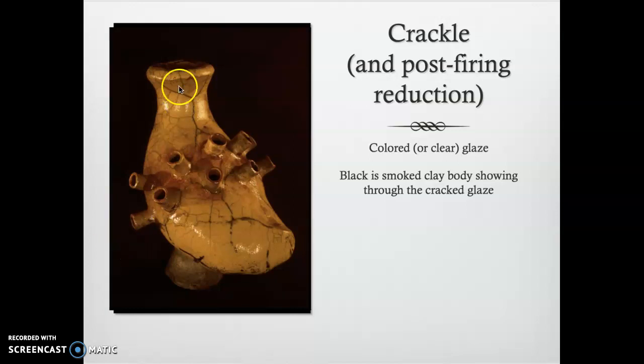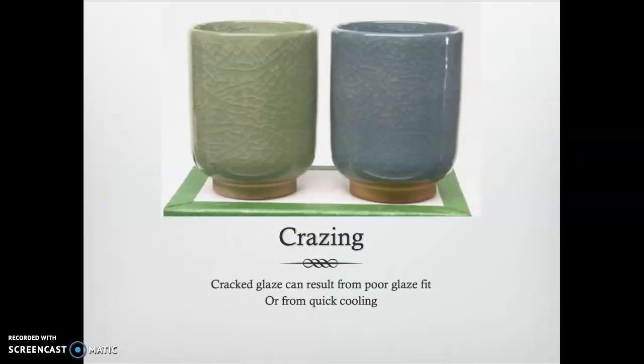And what we're seeing here is this crackle glaze. This is a yellow and red glazes that are crackles. What's happening is the glaze has cracked. We know this from talking about raku before. The glaze has cracked, and normally we might not be able to see that very well. But then this has been put in a bucket of combustible, so what we're looking at is smoke that we can see through the cracked glaze. Now, if we're not firing raku, we call that cracking crazing, and we think of it sometimes as a problem, right? A glaze fault.